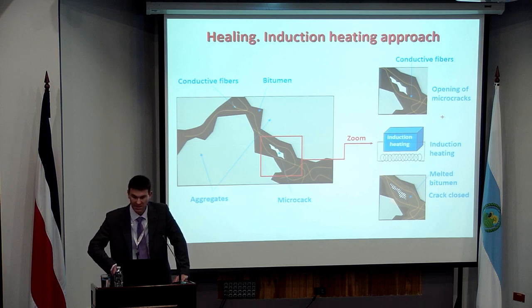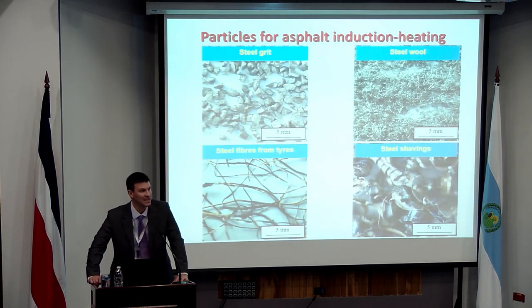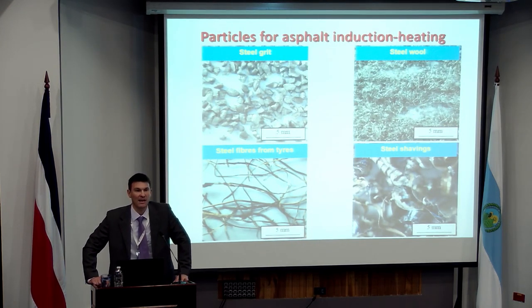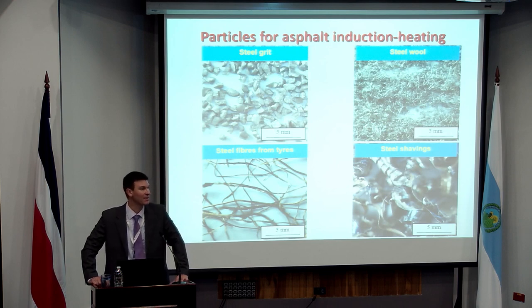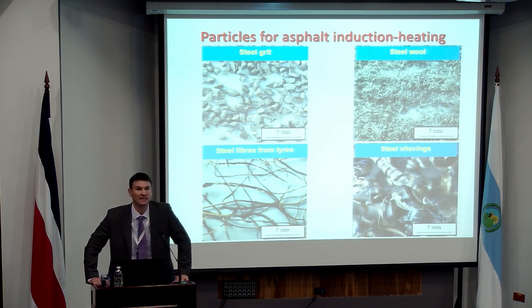What kind of materials will we use? Well, as I said, any kind of material that is going to be activated by using the induction heating approach. So we could use steel grit, we could even use steel wool, some kind of recycled fibers from car tires could be useful, or metal shavings. And we played around with all of these. Some of them are quite expensive and therefore probably not that practical. Some of them are already waste materials and don't add a massive amount to our final product.